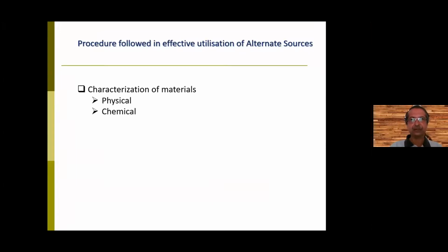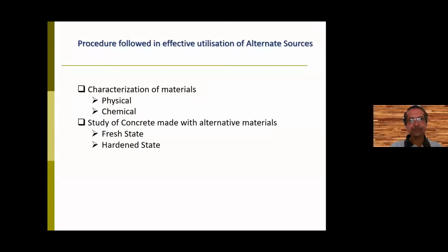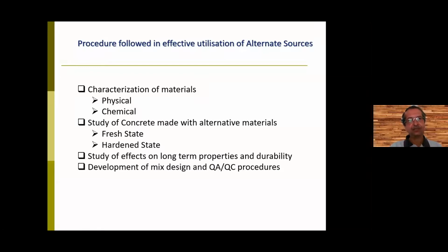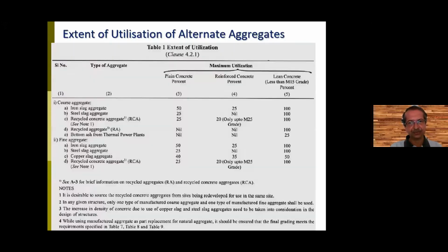So whichever aggregate you're planning to use, what you must basically look at before you choose the alternate source is to characterize the material physically and chemically, study the concrete made with that alternative material, again in fresh state and hardened state, study the effect on long-term properties and durability, and also develop a mix design appropriate to the alternate aggregate that you are planning to use. You may be completely changing from natural aggregates to alternate aggregates, or you may use a certain percentage of the alternate aggregates. Whatever you use, for that the mix design has to be modified many a time, and also there must be a QA/QC procedure laid down.